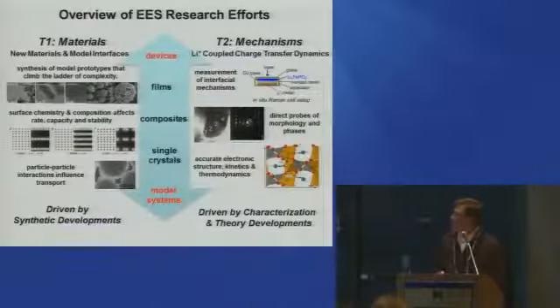So I moved away quickly in Joe's group from the aqueous solutions, because the problem was you have things like hydrogen evolution, oxygen evolution, bubble formation, dealing with very concentrated acids, and we moved into actually trying to do this first with lithium ions. So the modern advantages to several of the techniques that we've been developing is to really look at the spatially resolving power of light microscopy coupled with vibrational and spectroscopic techniques, where we can then use a series of these tools to shrink down the analytical spot size so that we can focus on issues of understanding how heterogeneity matters in this, and get away from these ensemble average measurements where you get convolution of the analytical signal.